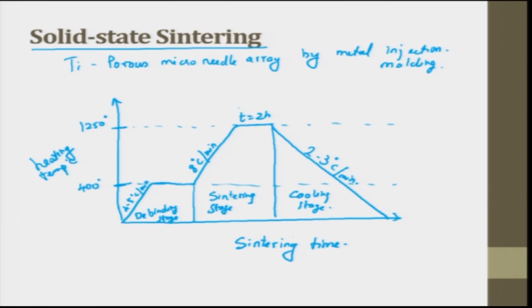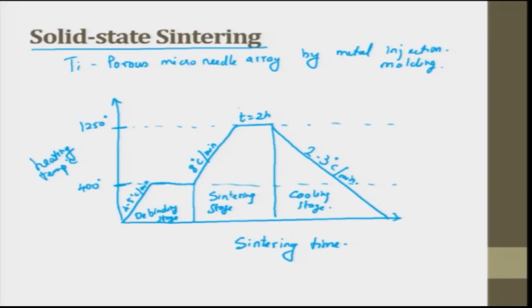First we have the debinding stage. Debinding stage means suppose you have some binder intentionally added so that it can glue and you can make a wet process. That binder has to be removed, so we call it the debinding stage, because we take it to 400 degrees. Generally we add the binder as a polymer. This is used only for the basic consolidation, or what we call green compaction. Then we heat it to 400 degrees Celsius, all of that is gone, and then you start slowly increasing the temperature. This process is called the sintering process, and this stage is called the sintering stage.